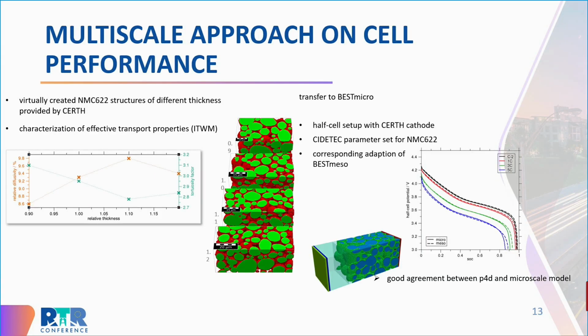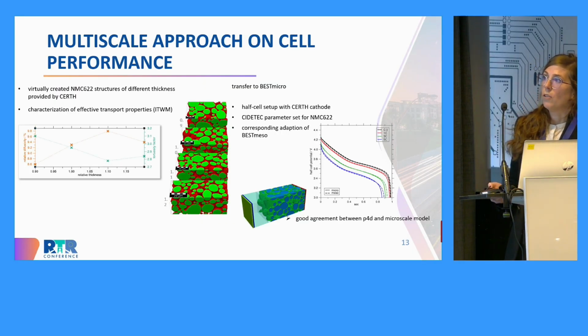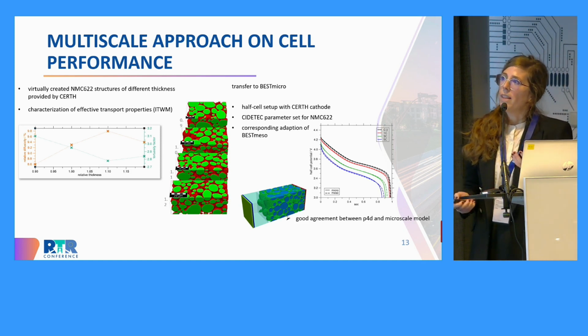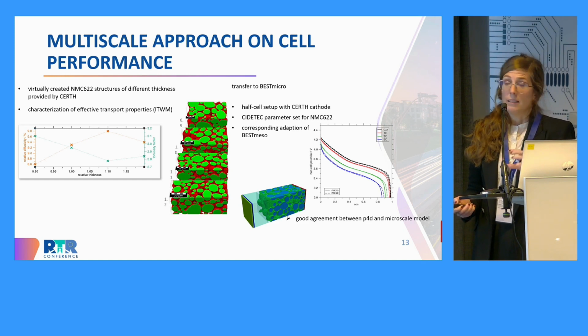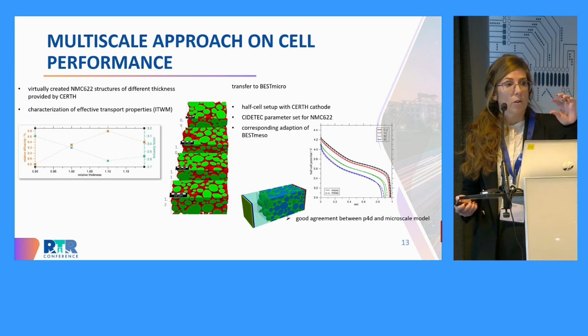So yeah, and then again the multi-scale approach, which is very interesting, because you are not only addressing the electrode at a homogenized level. The microstructure is a huge, very complicated system, and it might depend a lot on the fabrication step, as I was saying, but it will have a lot of impact on the performance. So the way you manufacture this microstructure determines the final results. This is another sample in which we are combining this multi-scale approach with, for instance, the calendering step and the pressure that the rolls applied.